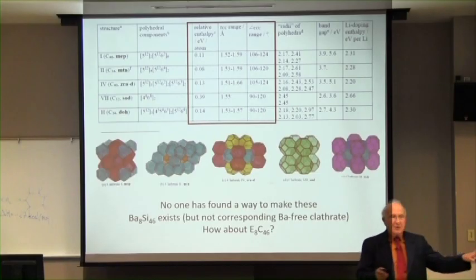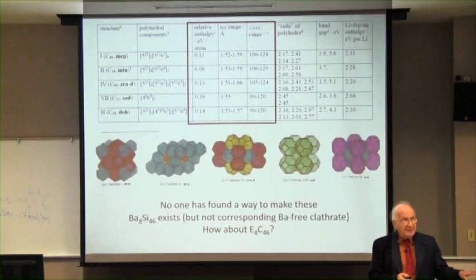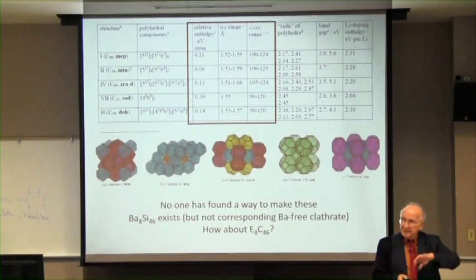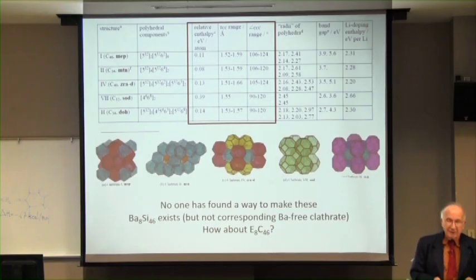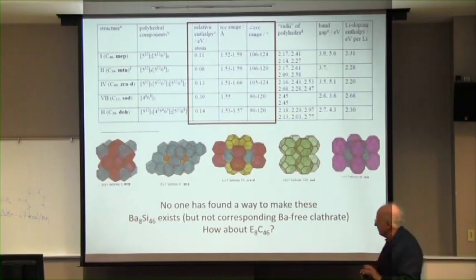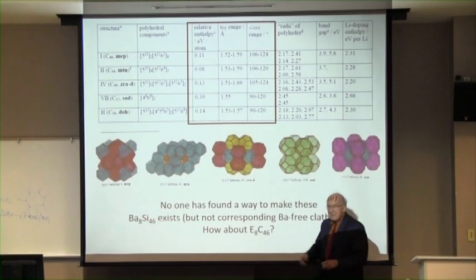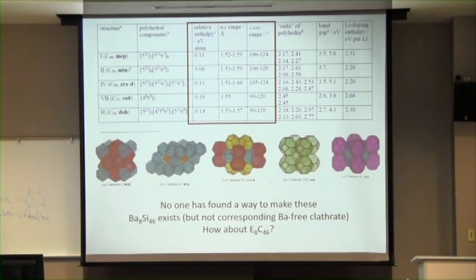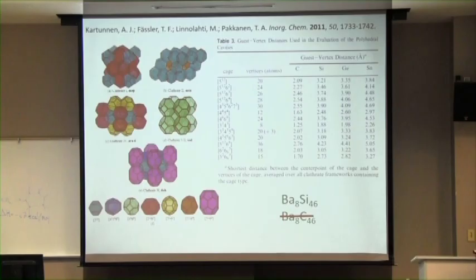Now, this is another story. That is how people make zeolites. So people make zeolites by taking an organic molecule, condensing silica around it, and then burning away the organic molecule in the middle. So we're not going to quite do that, but maybe could we make something with something in each carbon polyhedron, which is stabilizing it. So in this beautiful paper by Kartunen and Fessler, they looked at every one of the building blocks of the zeolites, and they calculated and compared with experiment the center to vertex distance of every one of these polyhedra. They're essentially calculating how much room there is inside.